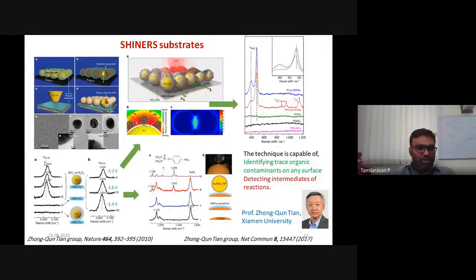And if you go through these three curves from top to bottom at different potentials, you are seeing the clear Pt-H vibration peak in the Raman spectrum, when you put a nanoparticle with just a 2 nanometer shell. It means when you reduce the shell, you start seeing the features. So it actually enhances when you reduce the shell thickness. And a similar thing was demonstrated with alumina. The first study was with silica. The second study is demonstrated with an alumina layer, and with the same pattern, with the increase in potential, you are seeing an increase in peak intensity.